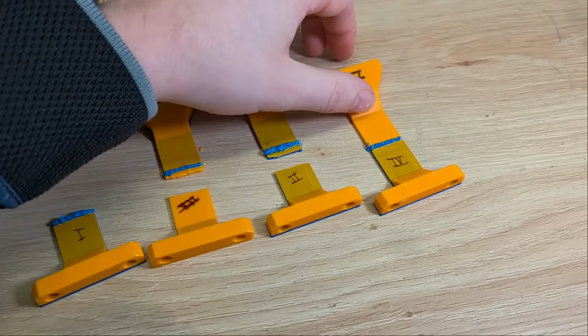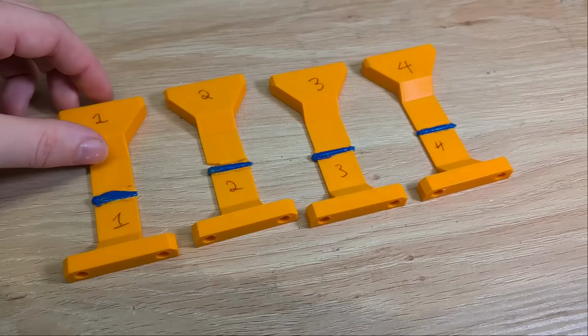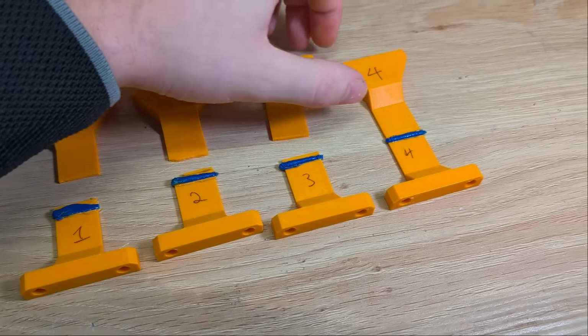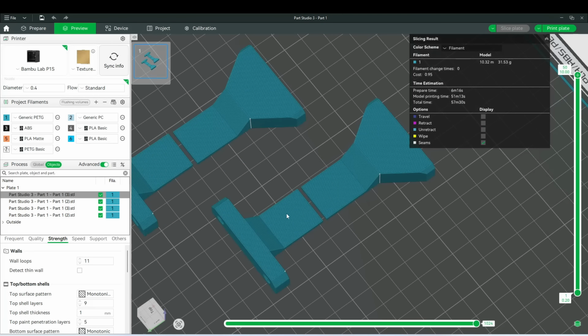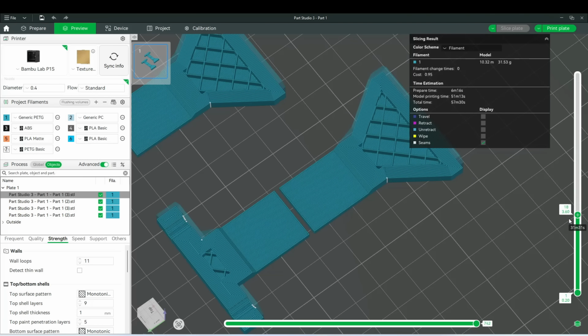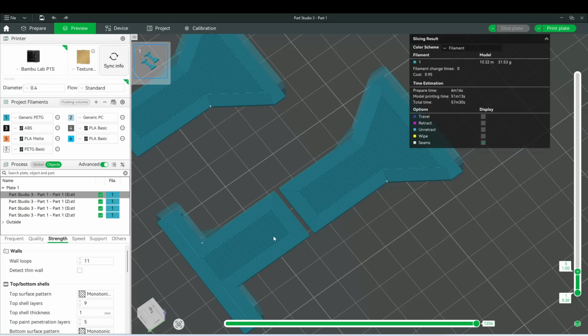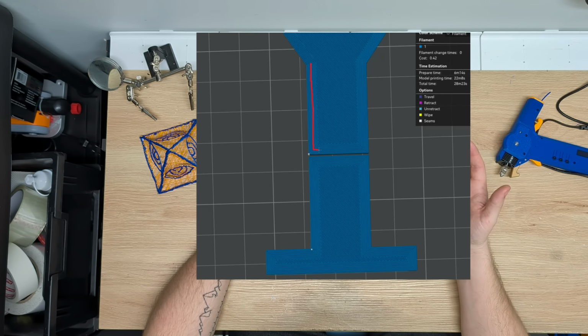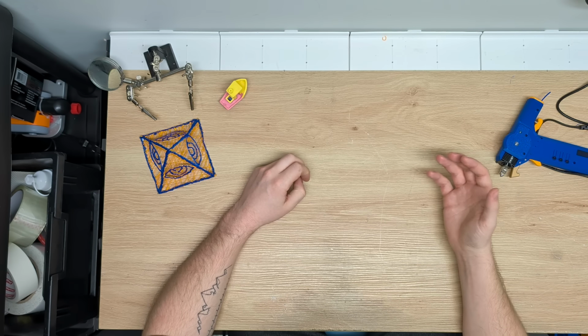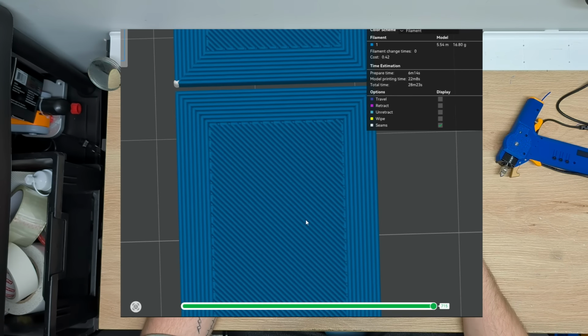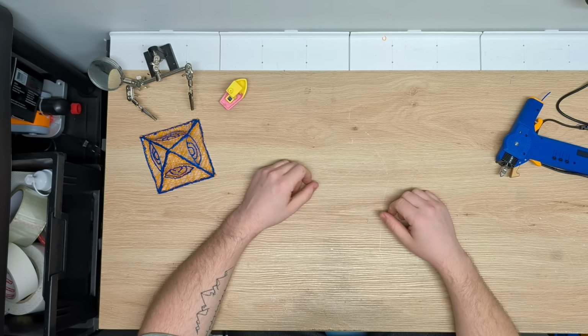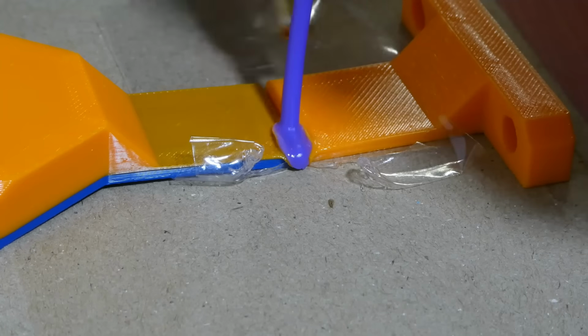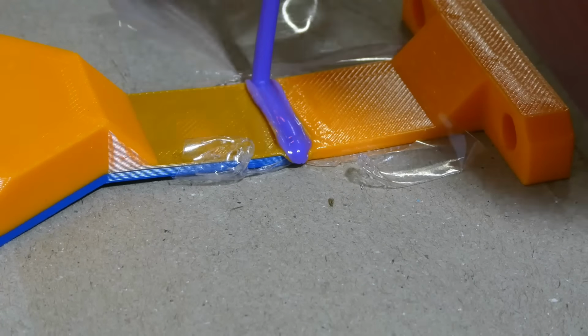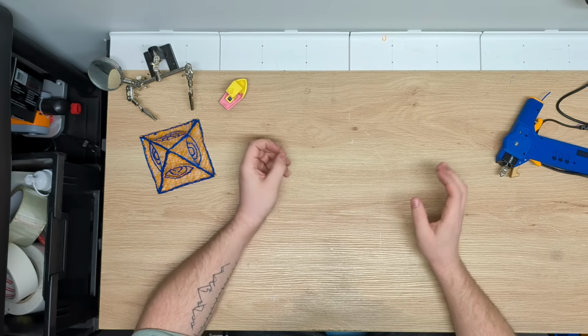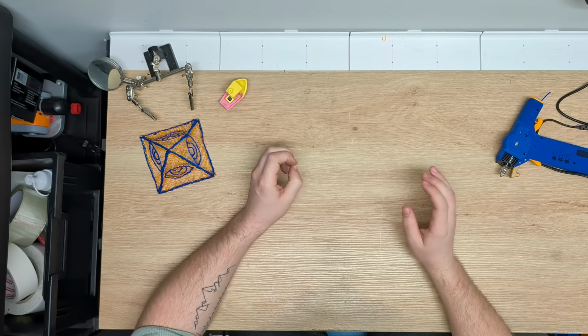Many of the welded samples did not fail at the actual weld location, but they did all fail near it. All the samples were printed solid with 100% infill and 8 perimeters, and if they didn't fail at the weld, they failed in this area. This is where the perimeters transition from vertical to horizontal. My theory is that the perimeters and the infill were not bonded perfectly as printed. So during the hot air welding, the extra heat from the hot air helped join these layers together, improving strength, whereas all the other samples, they weren't actually bonded perfectly.